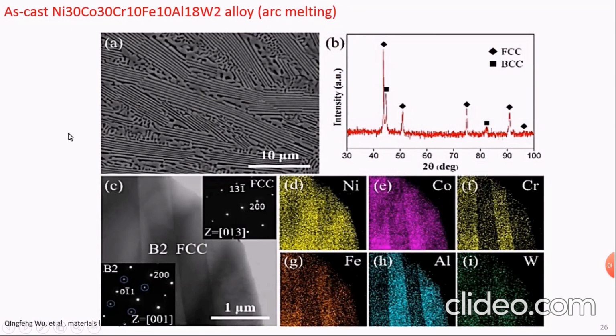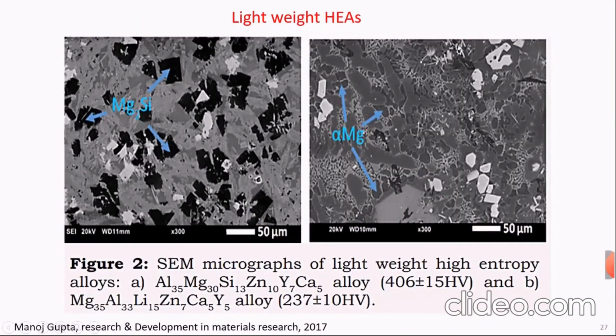Some other people, Wu et al., prepared the alloy by arc melting: nickel, cobalt, chromium, iron, aluminum, tungsten alloy. And as you see, they have two phases, FCC and BCC. And this is the elemental distribution of the different phases. Actually, high entropy alloy is a very interesting alloy, as you see.